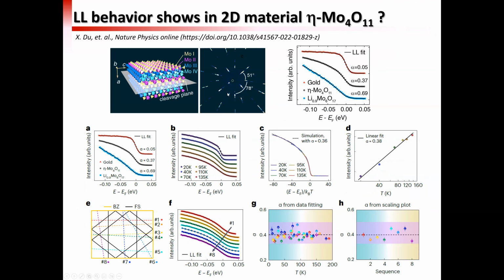But interestingly, recently we found this two-dimensional material, the eta phase of molybdenum oxide, and it doesn't have an obvious one-dimensional chain. The data show the high quality of the material, and also show the two-dimensionality of the material. And surprisingly, they also show Luttinger liquid behavior. We were wondering why this would happen, because clearly, you can see from the structure here, it is a 2D plane.